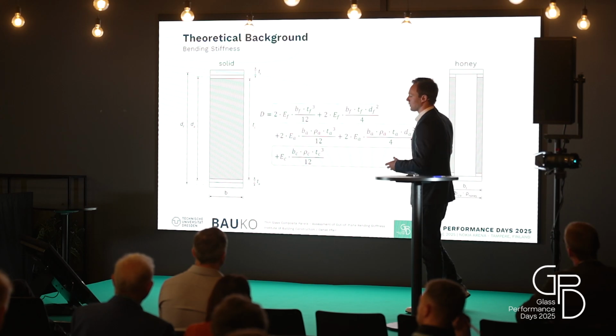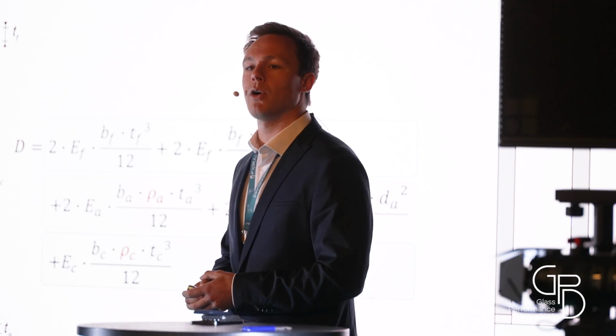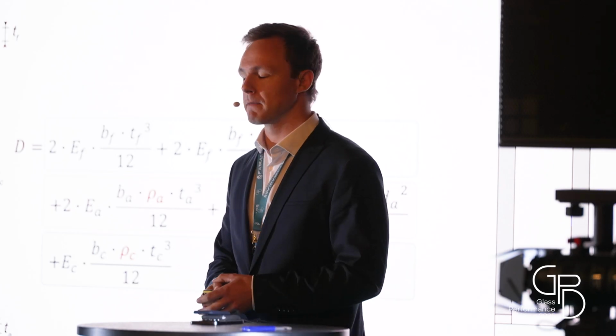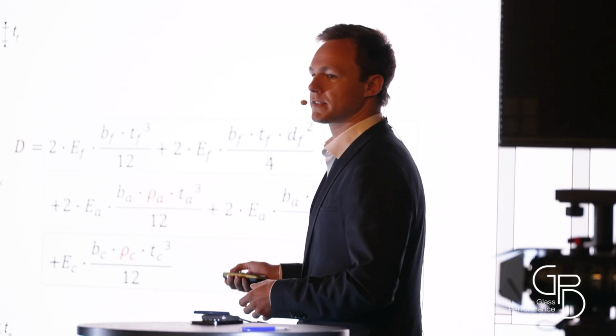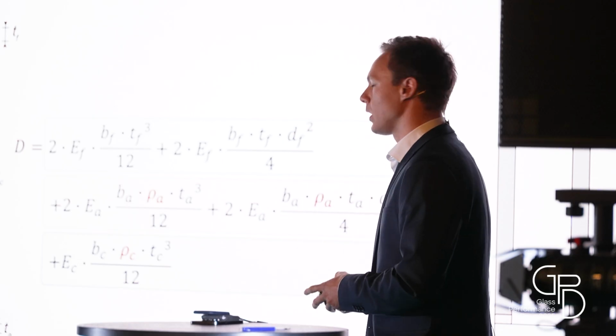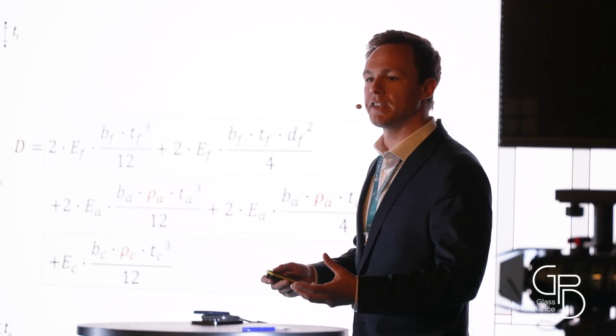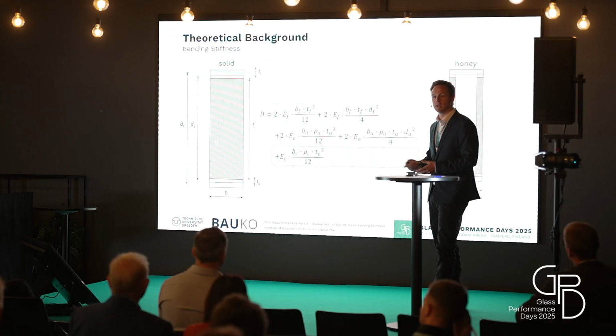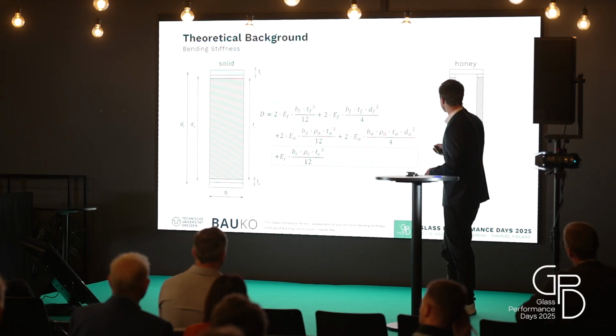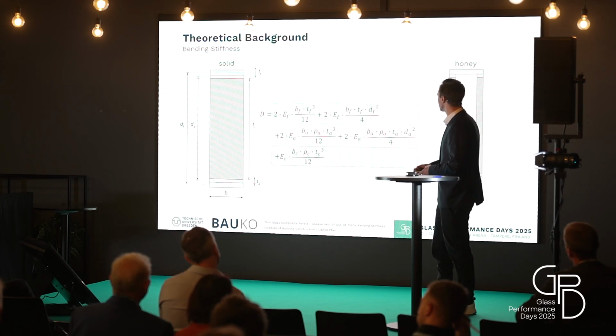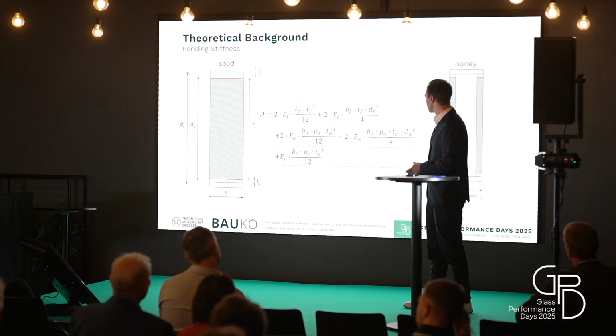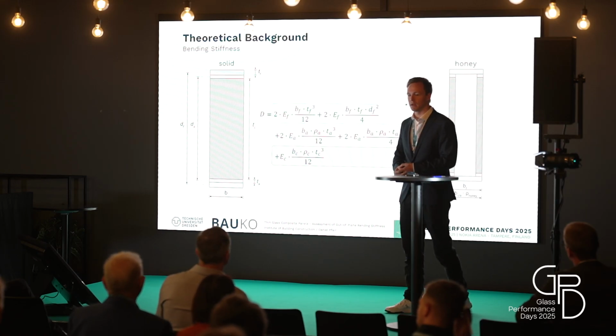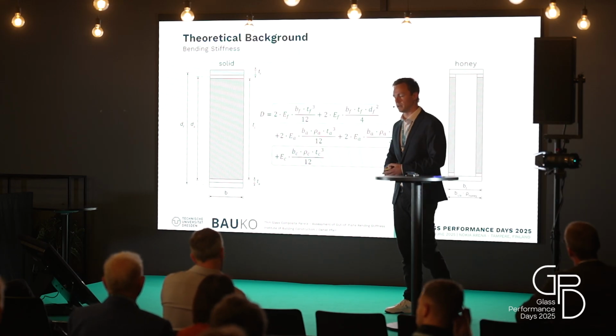And on the other side, we can try to account for the honeycomb structure we are using. So we need to incorporate something into the bending stiffness to account for the lower density of our core structure. In that case, the honeycomb structure, or the density of the honeycomb structure, is represented by a factor multiplying the width of the whole composite.